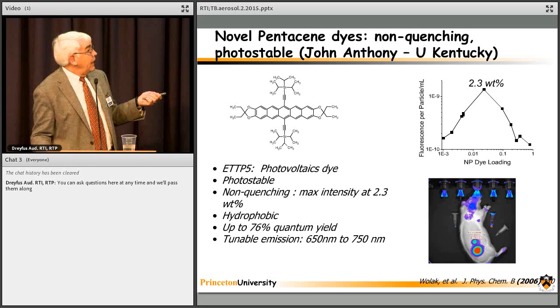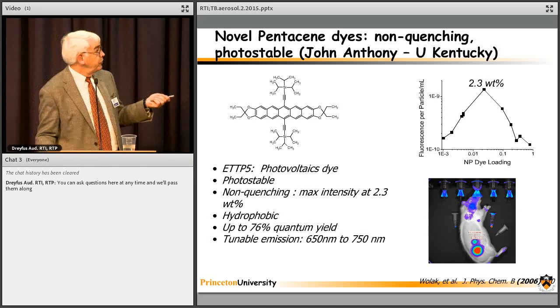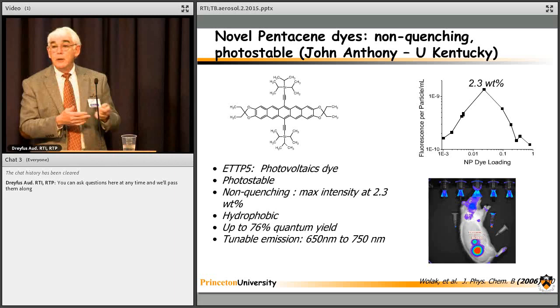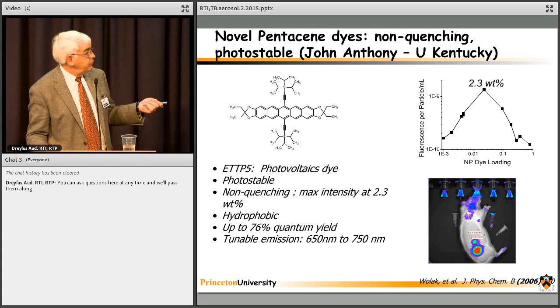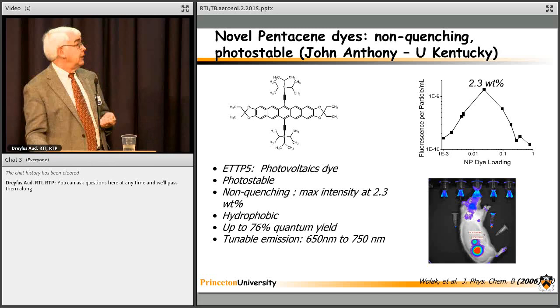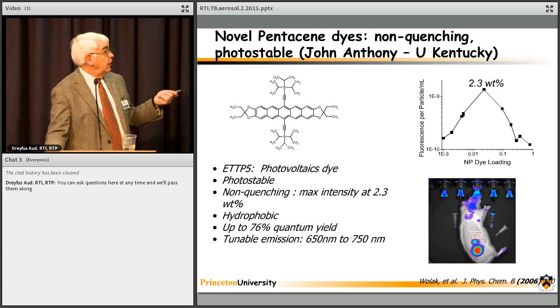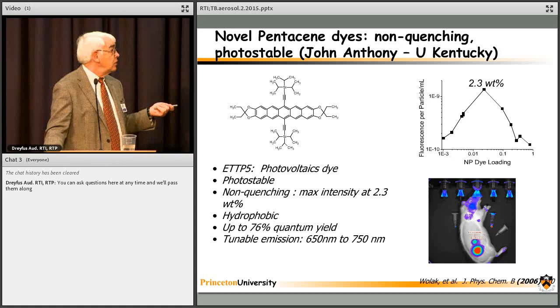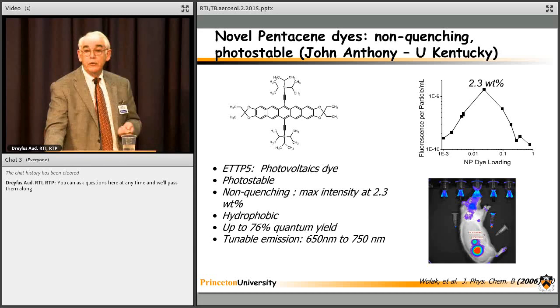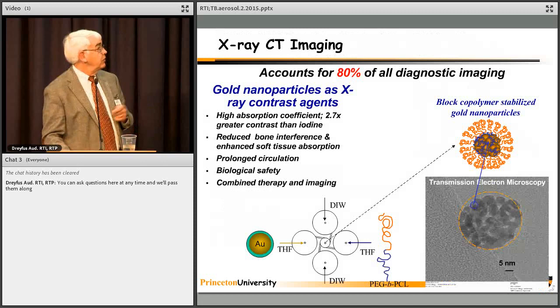We now put these in the nanoparticles at about 2.3 weight percent. This is the fluorescence per nanoparticle, and this is concentration. If you go to too high a concentration, you get Förster energy transfer and quenching, but 2.3% gives you the maximum fluorescence per particle. And this shows an injection into a tumor in a mouse, so we can do IVIS imaging with these particles. They're photostable, they're non-quenching, you go to this maximum, they're very hydrophobic, they have 76% quantum yields, so they're quite efficient, and the emissions are between 650 and 750. This strong emission is about 650, which is a little too short for some of the whole animal imaging that we're now doing, but that's a dye we often use.